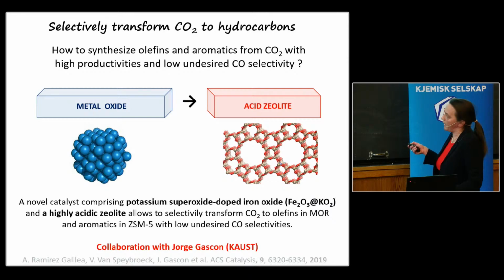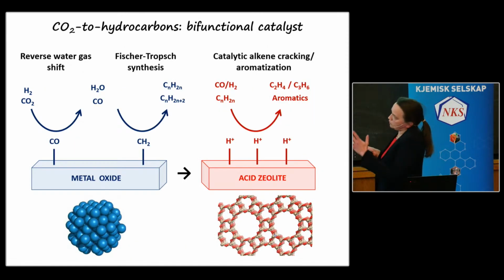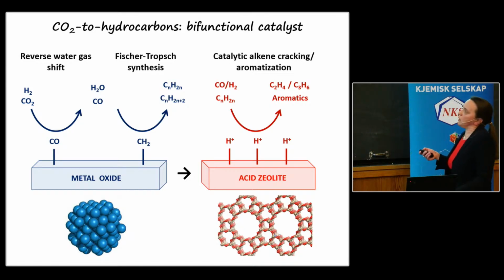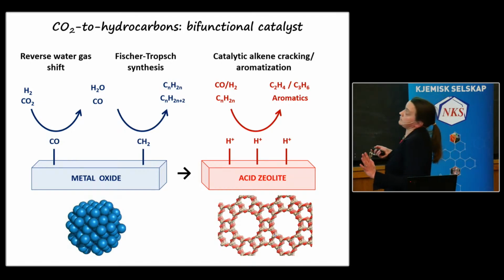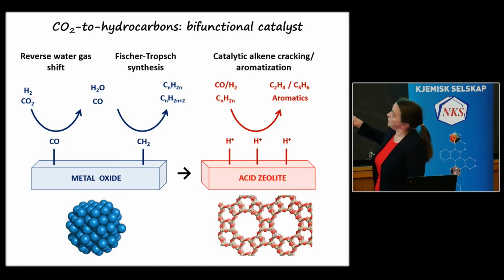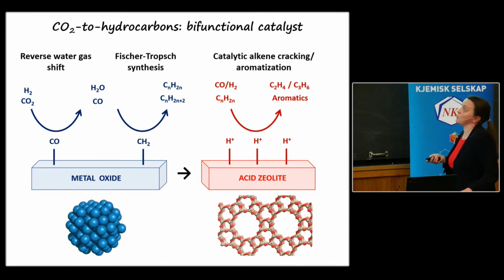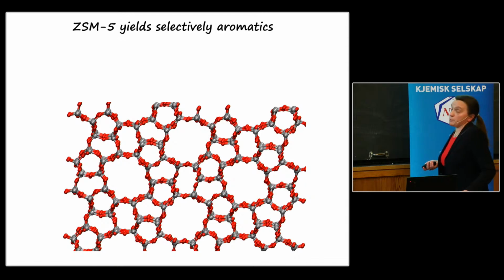So we have a metal component, we have the zeolite component, and what they found is a very good catalyst to selectively transform the CO2 indeed to the hydrocarbons. So they came to us because, so this is a little bit more in detail the chemistry. Here you can see the reverse water gas shift reaction, and then the Fischer-Tropsch, and then here is the zeolite. Here you have the longer hydrocarbons, which you can selectively make into ethene, propene, aromatics. And what they found is that if you use a particular zeolite here, you can selectively form these small alkenes, or you can selectively form the aromatics. They use two types of zeolites to do that.